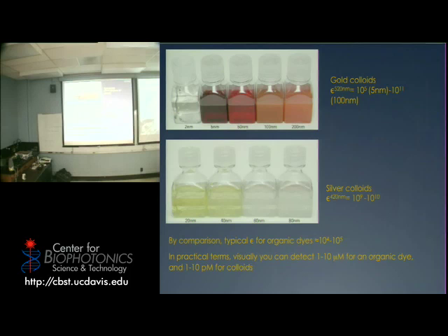It doesn't look like gold, but it is. Gold, you guys all know how it looks. It becomes red because around 520, 540 nanometers, it absorbs light. What's left gives you the impression of being red, and that's how they look. And as you can see, they're suspended, they're transparent, and don't have any interest in precipitating off. Also, because of the resonance, the capacity of this material to absorb light is huge.